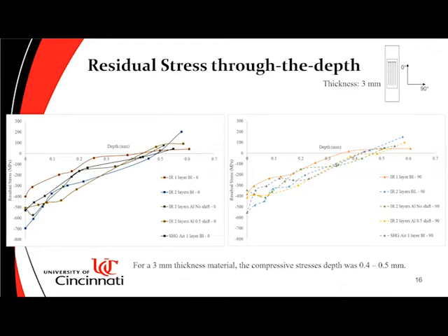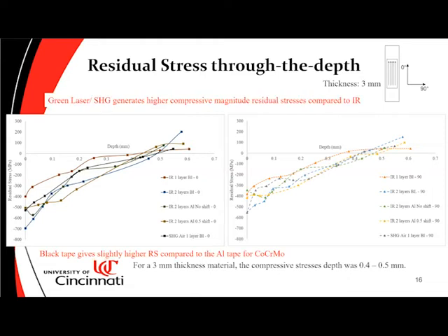For this particular cobalt-chromium alloy, as shown, the black tape gives slightly higher residual stresses compared to the AL tape. Also, the green laser generates higher magnitude of compressive residual stress compared to the infrared. So we see here, this is the black tape, and this one is for the green laser.